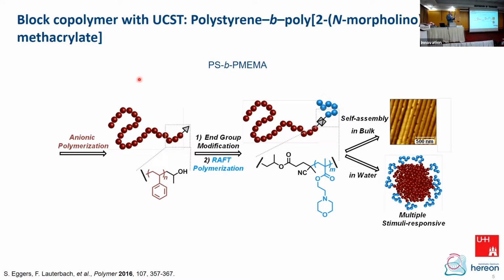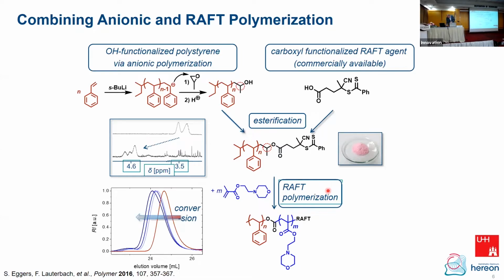But anionic polymerization, that's simple. So the idea was we use anionic polymerization to generate polystyrene. We end-functionalize this polystyrene with an OH group, and then we connect it with a RAFT agent, and then we do the RAFT polymerization of the second block. So it's a combination of anionic and RAFT polymerization, and this was done very successfully. So from a certain batch of polystyrene, different lengths of the second block, this N-morpholino ethyl methacrylate, was polymerized, and Stefan achieved here different structures. So this is just the chemistry.